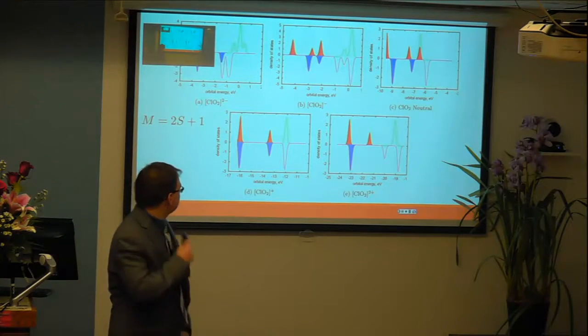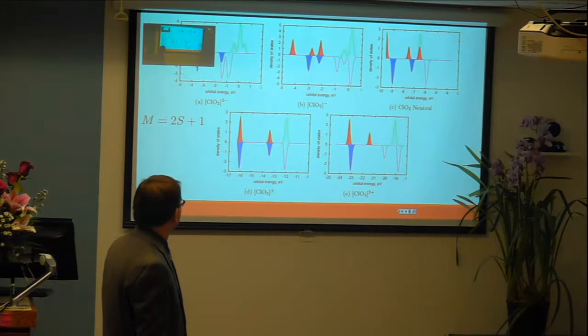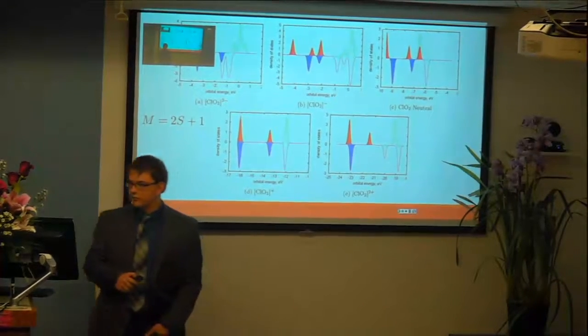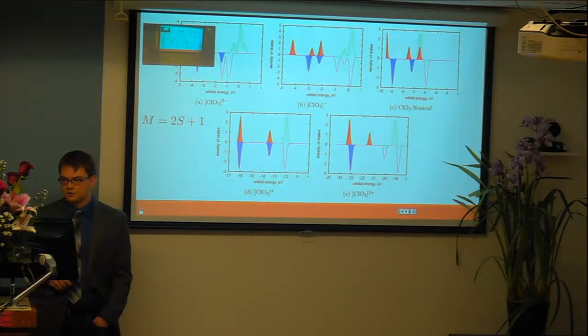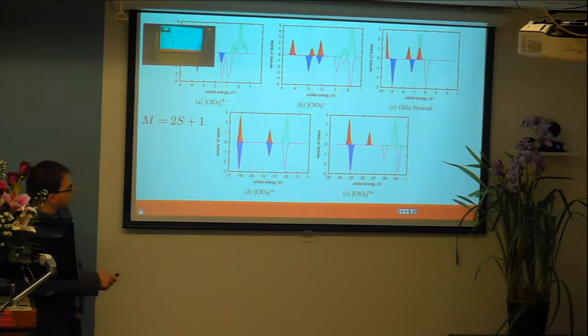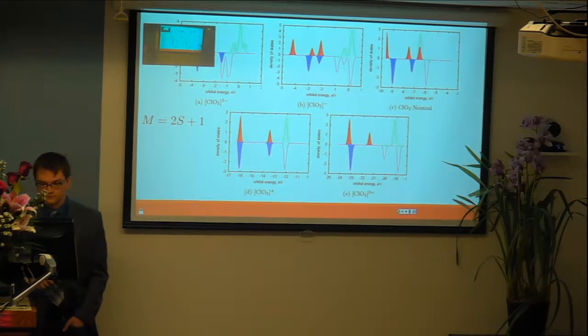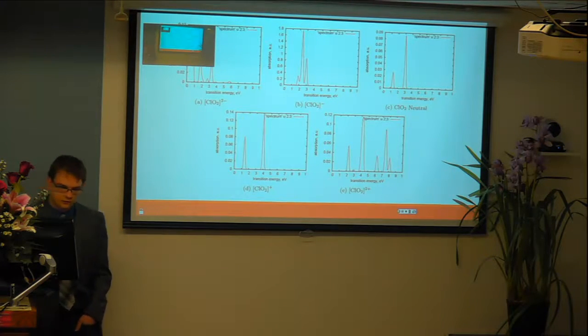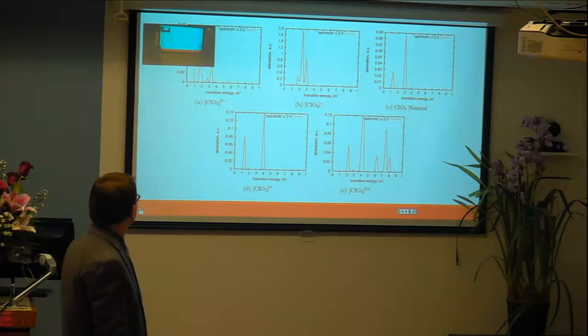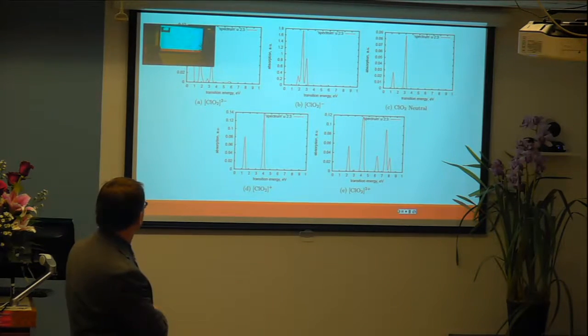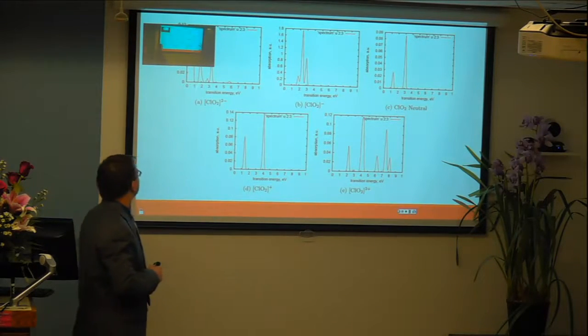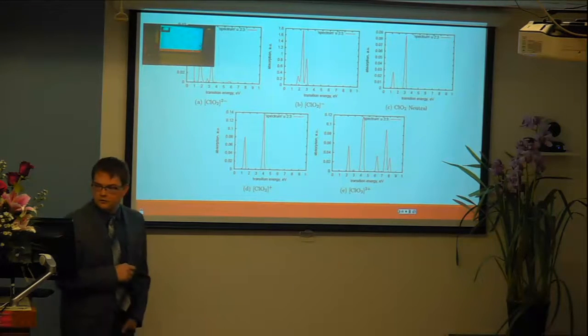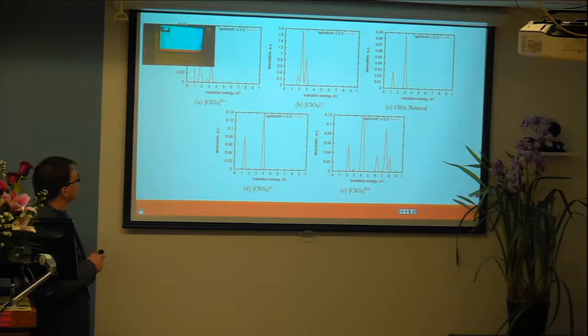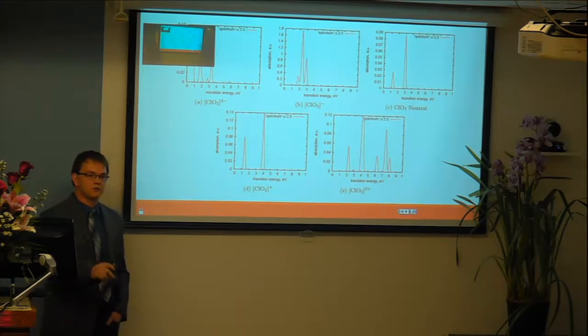So here's the density of states for each of the structures. You can see that the bands themselves are pretty distinct, for the positive ones separated by many electron volts difference. More interesting to note are the ones that look a little bit more reasonable. The absorption spectra are shown here. For chlorite, because the occupations are so close, we see a large bump in the absorption energy because it's occupied next to unoccupied, so that's discussed in a previous presentation.